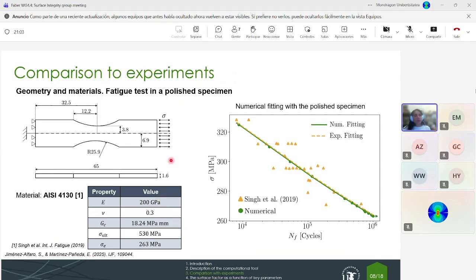So now we compare our results to experimental data. We have used an experimental campaign done by Singh et al. in 2019. It was done on a material that was AISI 4130. You can see here in this table the material properties reported. It was a really interesting experimental campaign because it gives us all the data we need. They analyzed, first of all, the polished specimen without any roughness, and then they included two different values of the average surface roughness, and they studied the effect that it has in fatigue.